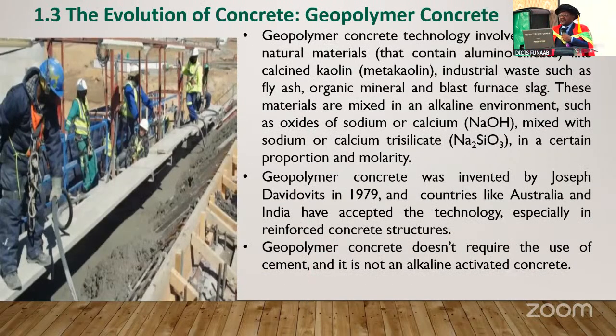Geopolymer concrete. Geopolymer concrete technology involves the use of natural materials that contain aluminum silicate like calcined kaolin or metakaolin, industrial waste such as fly ash, organic minerals, and blast furnace slag. These materials are mixed in an alkaline environment such as the oxide of sodium or calcium, mixed with sodium or calcium silicate in a certain proportion and molarity. Geopolymer concrete was invented by Joseph Davidovits in 1979, and countries like Australia and India have accepted the technology, especially in reinforced concrete.